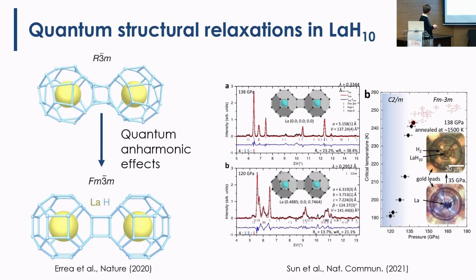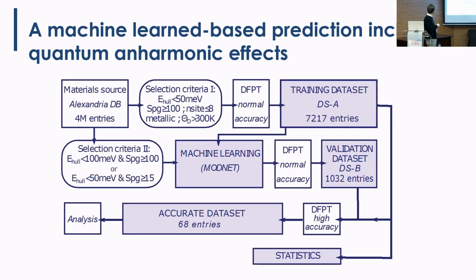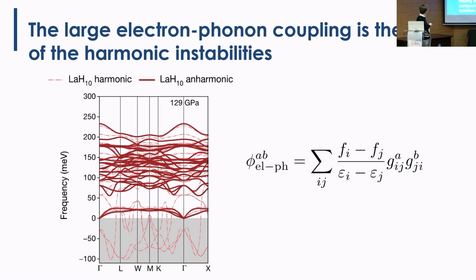So let me just tell you this story. So this is, for example, lanthanum H10. We applied this to many hydrides, H3S, lanthanum H10. We've been working on charge density wave materials, ferroelectrics. So these ideas are important for all these kinds of systems. But what I mean here is that this is lanthanum H10, which is experimentally well understood, it's a solid, and has a critical temperature of 250 Kelvin at around 150 GPa. If you calculate the harmonic phonons, you get them completely unstable. The structure that you observe experimentally is not at all stable.